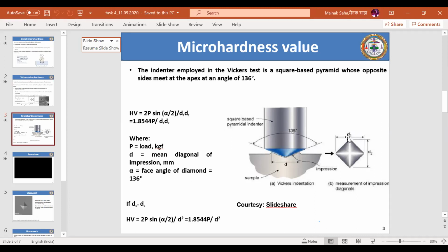For example, like I have already given you an example. My stream that I was working on, during third year of BTech. So I had, in the first year with 1 kg of load, a hardness of around 200. Second, I was also quite curious to know about things. So what I did, I changed the load to around 2 kg and then tried to find out what is the hardness. Now I found the hardness value to be around 203. There is not much change, right? 200, 203, scientifically, they are very close. I mean, they are within error limits, right?